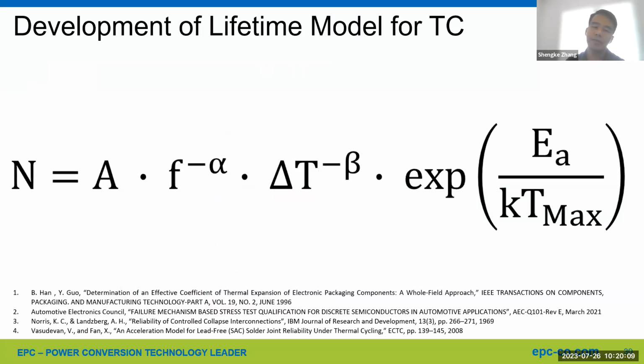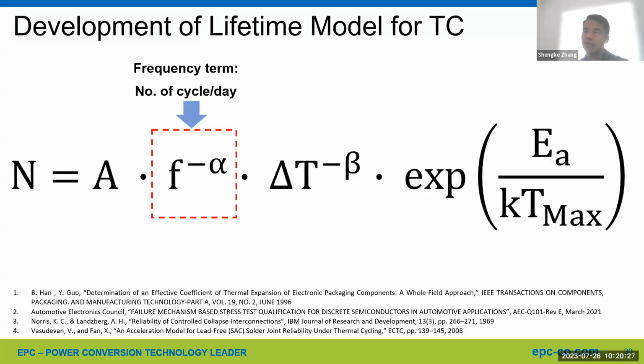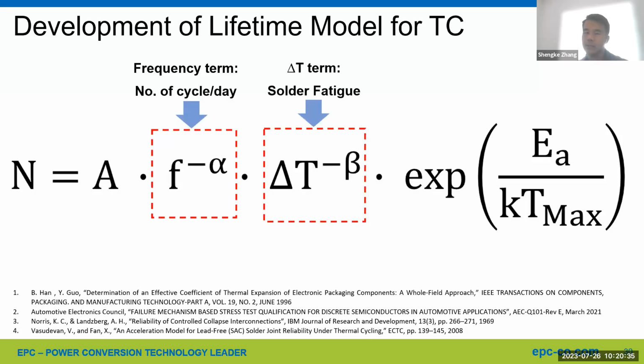Based on this test to fail and viable data, now we are able to develop a general temperature cycle lifetime model as shown here, which is known as the Norris-Landzberg model. N on the left is the number of cycles to failure. A is a coefficient. The first term is a frequency term, which includes how many cycles per day during this temperature cycle testing. The second term is the delta T term, which is the classic Coffin-Manson equation. This term focuses on the solder joint fatigue wear out mechanism.